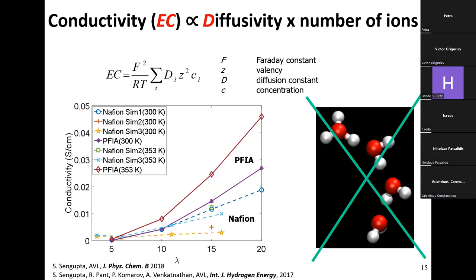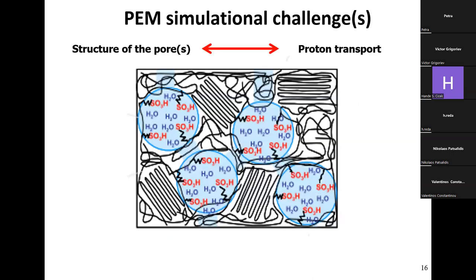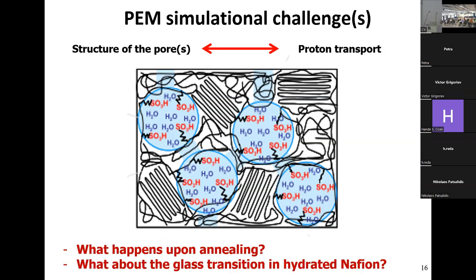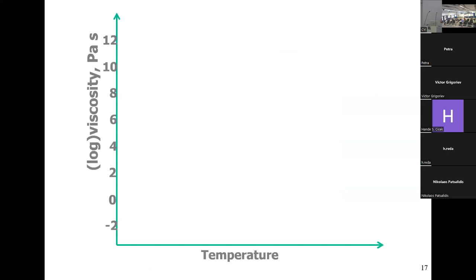Connecting the pore structure of the membrane to proton transport is a big challenge. Experimentally, a fresh Nafion membrane left to age — a process called annealing — shows drastic changes in proton transport. This leads to an important question about glass transition in hydrated membranes: can we even speak of glass transition when water is present inside? Upon aging, vitrification takes place and this affects water transport and proton conductivity.